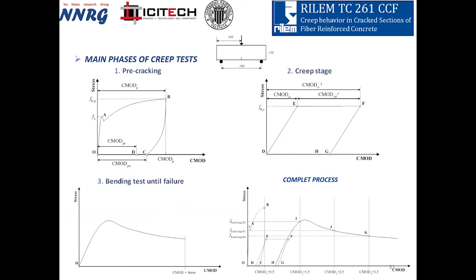In a creep test, usually, thinking in a flexural test, for instance, but similar applicable to the others, we organize a specimen, in this case a pre-cracked specimen. We apply a load until crack and residual crack opening. We have the residual capacity. We unload the element. Then we have this element that is pre-cracked. And this element that is pre-cracked, we send to the creep stage.